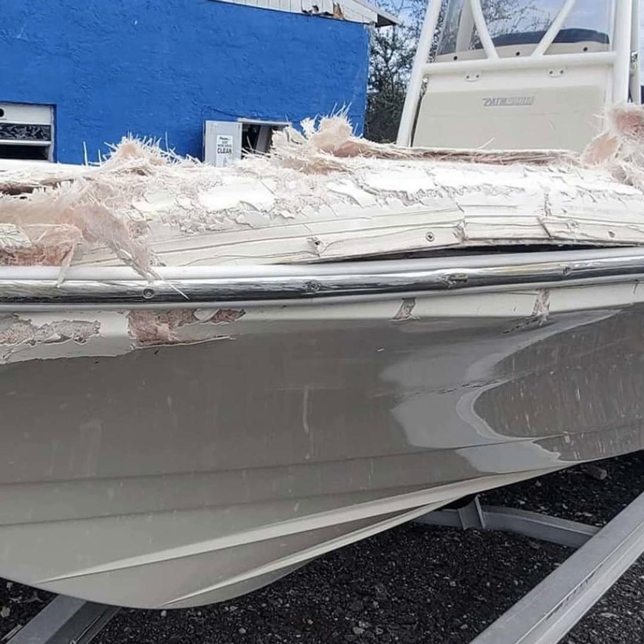If you start getting into things that you're not sure what you're working with, or you're not able to identify what resin you have, and maybe it's a jet ski, maybe it's one of those sheet molded composites or something like that, or the nano cell, whatever Yamaha did with their skis a little while ago. When in doubt, you can use epoxy. The rule of thumb when you're using epoxy is that you can stick epoxy to anything, but you can't stick anything to epoxy. Polyester and vinyl ester resin will not bond to epoxy resin. So once you start going down that epoxy road with your resin, then you're kind of committed to that.